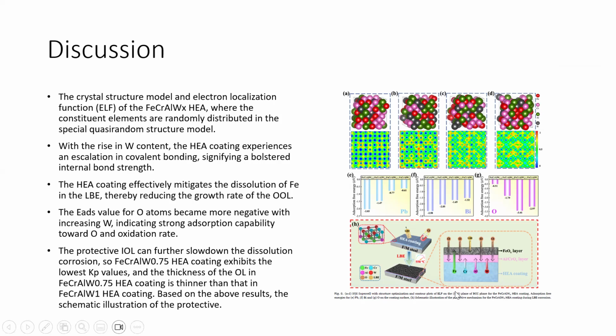The protective inner oxide layer can further slow down dissolution corrosion. So the FeCrAlW0.75 HEA coating exhibits the lowest Kp values, and the thickness of the oxide layer in the material coating is thinner than in the other tungsten variations. Based on the above results, the schematic illustration of the